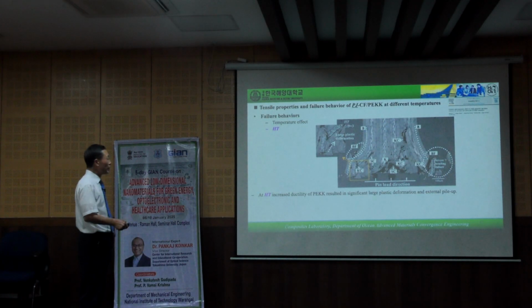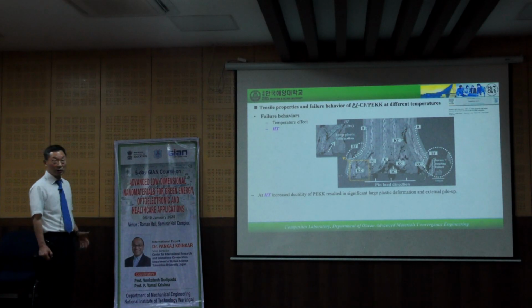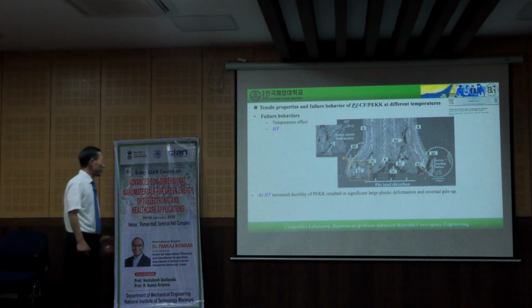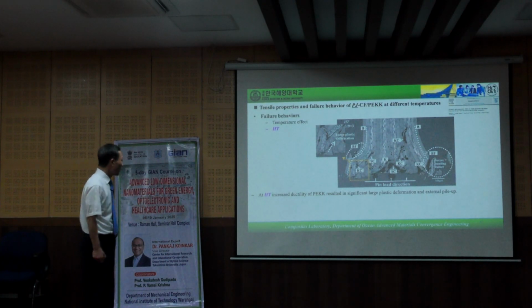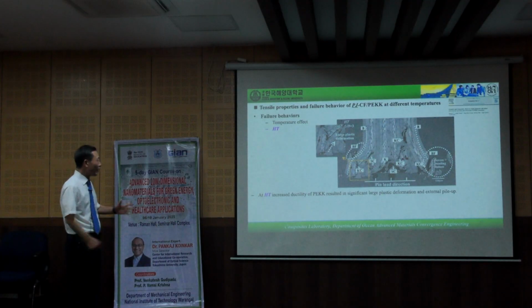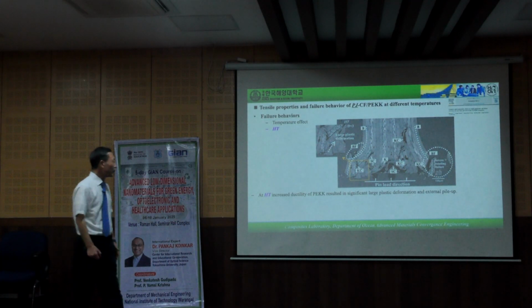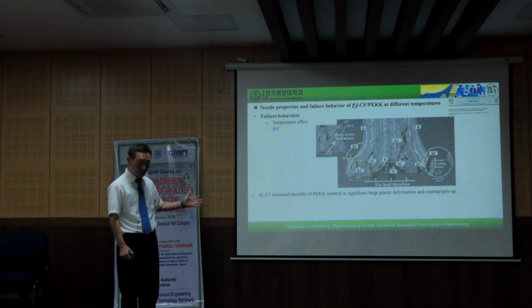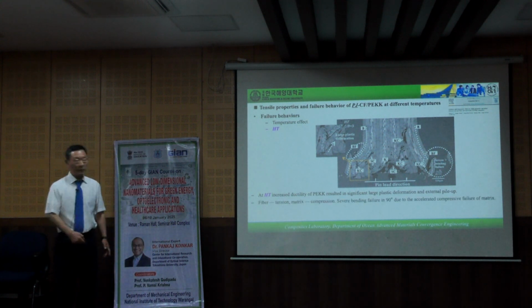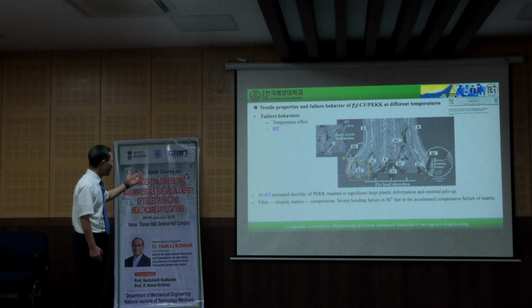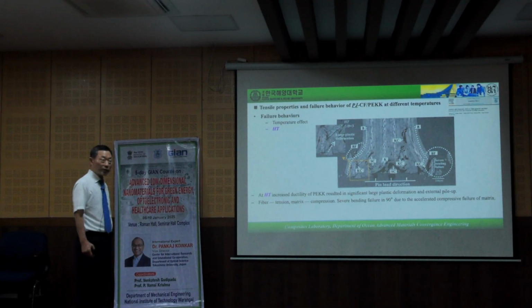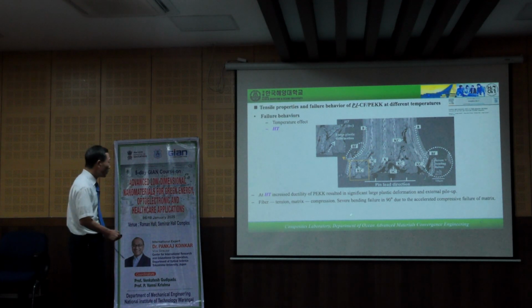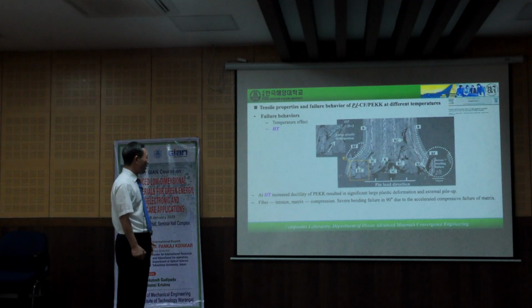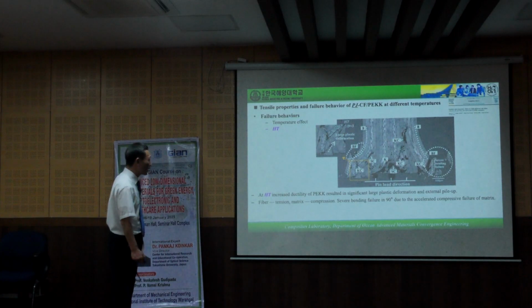At high temperature, we can observe the cracks pattern like this. At high temperature, increase the ductility, right? So increase the ductility of a PEKK resulted in significant large plastic deformation and external pile-up you can observe. In this case, fiber under tension, matrix under compression, right? So the severe bending failure in 90 degree due to the accelerated compressive failure of matrix.